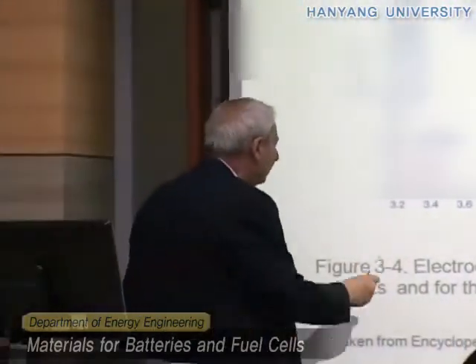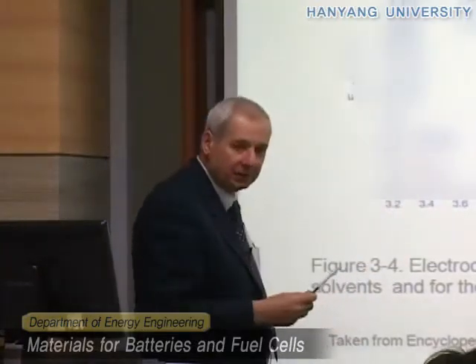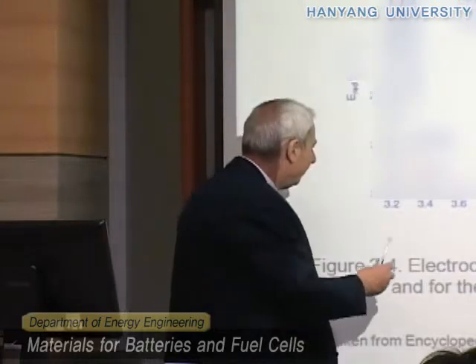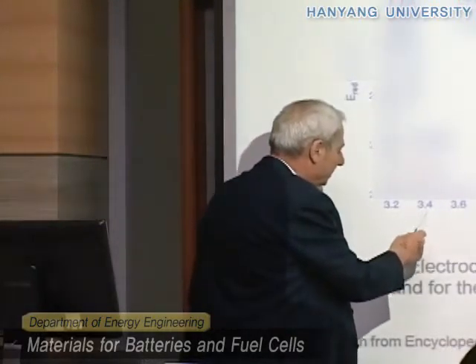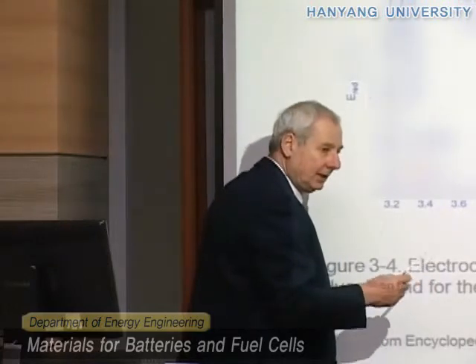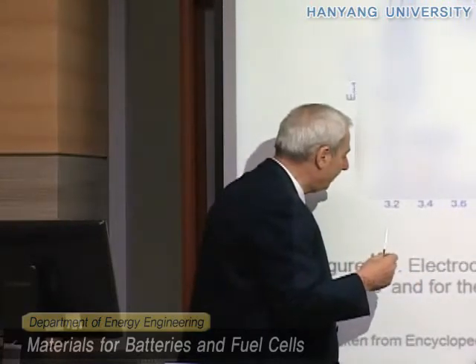Here you have water, which of course cannot be used with lithium batteries because it decomposes at around 3.4 volts — around 3 volts versus lithium, or 1.23 volts versus hydrogen. So water is a problem. In fact, at any moment that you have a drop of water in your battery, it will decompose.